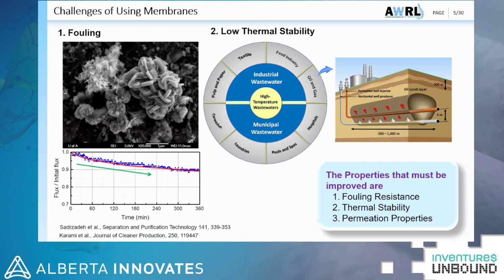But there are some challenges to using membrane technology in SAGD. First, the membrane can be fouled and scaled by silica, organic matter, and the hardness of the SAGD produced water. This reduces the flux significantly over time, and therefore chemical cleaning and backwashing should be done more frequently. Again, this increases the operating cost and decreases the lifetime of membrane. The second problem is the high temperature of SAGD produced water, which ranges from 70 to around 150 degrees C. The commercially available polymeric membrane cannot tolerate this temperature.